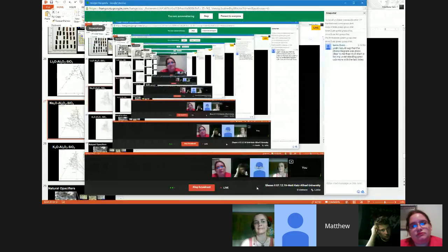that comes back to my terrible lemon test. This is essentially a high sodium glaze, and yeah, it's based in silica, but it fails because there's too much sodium, and sodium silicates are weak bonds. Okay, easily dissolved by acids, by water, by all of that stuff. So again, that even goes all the way back to, why do we use 2 fluxes? We could make a glass that is just sodium fluxing out silica, and it sucks. Okay, it does no good.